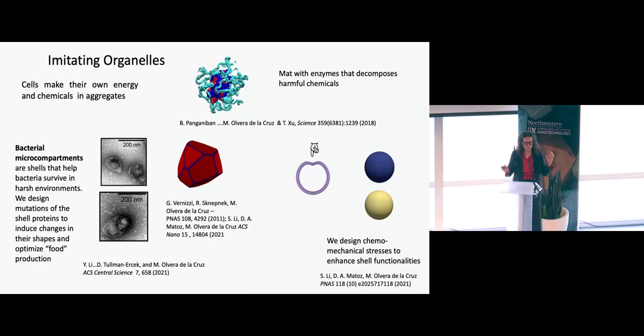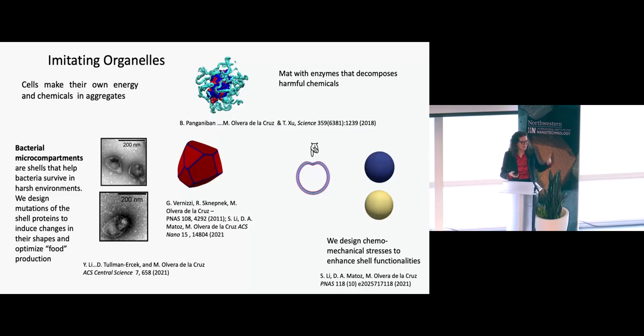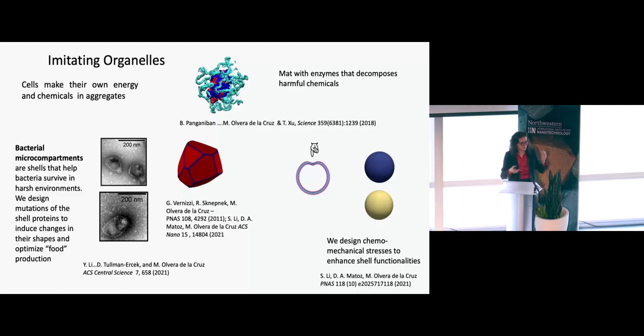Here is an example of a patterned polyhedra. Viruses can be spherical and as they grow they buckle into an icosahedra. But what we discovered theoretically is that if you mix two components, you can form much more complex polyhedra. For example, the red color represents very rigid molecules, and if you co-assemble them with ones that are more easy to bend—the blue ones—they form this very complex decorated shape that when you look at the actual micro-compartment, they look identical.